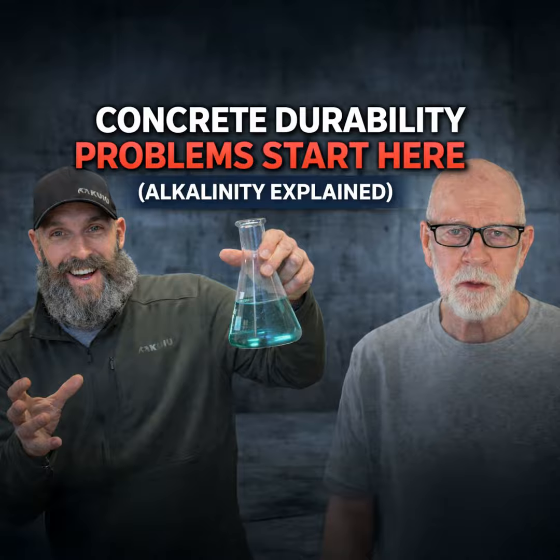That will damage the concrete surface, because now it's dehydrated, but it looks wet. You go, well, what's wet? Why is it cracking? Well, because that is not available to the cement. So that's why the top surface of the concrete, in the first inch, self-desiccates, and that will even happen in a laboratory. When Texas Transportation Institute did the study, I believe it was back in 2005, they water cured the concrete for 7 days. When he isolated the top 1 inch of the concrete, it was a full 20% lower in compressive value than the remainder of the concrete. That shows there's a lack of strength gain. And the lack of strength gain means that the cement is not properly hydrating.